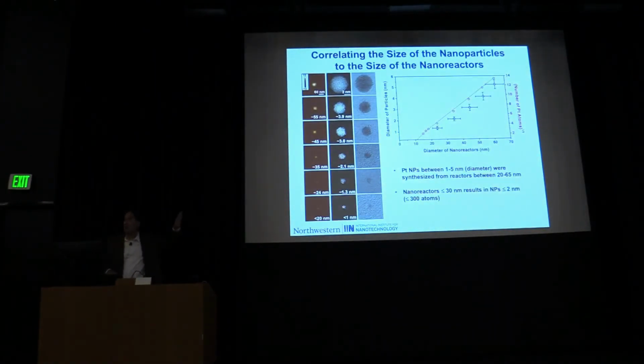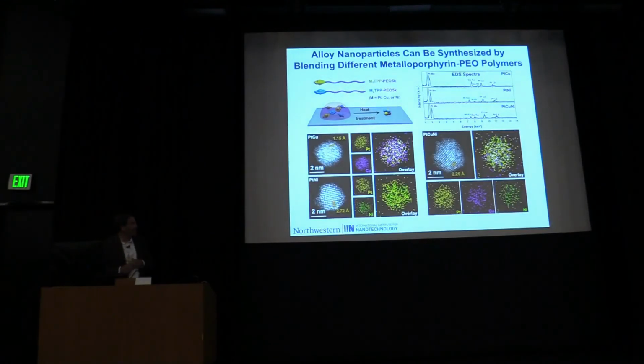You're literally at yoctoliters of volume in the reactor. These are really, really tiny controlled systems. And here you can see we can then take these polymers that are end capped and we can now begin to mix them, right? So that we can build these tiny particles: platinum, copper, platinum, nickel, platinum, copper, nickel. So we can begin to play that game as well.